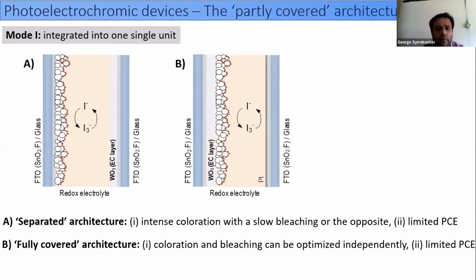When we started to work on photoelectrochromic devices, there were two different device architectures, the separated one and the fully covered one. Both of them had a very thin, transparent titanium film. In the case of the separated architecture, the electrochromic layer was at the cathode. In the case of the fully covered architecture, the electrochromic layer was placed at the anode, and we also had the platinum film at the cathode. Both of them had their own advantages and disadvantages, but the common issue was the limited photoconversion efficiency.